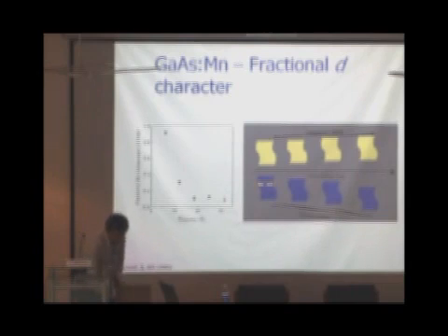So that's like the 3d electrons of manganese over there, manganese 2 plus goes into gallium 3 plus, arsenide 3 minus. So it's a hole doped system. We have just 4 electrons, 1 for the hole. Okay. So since this is lying deep in the valence band, it can't be hole doped. So the hole has to float to the top, so the hole comes on the top.